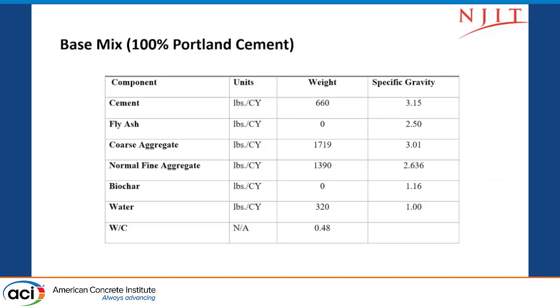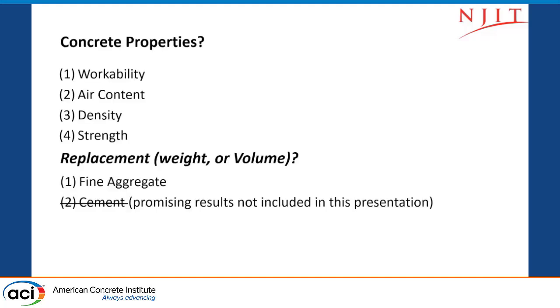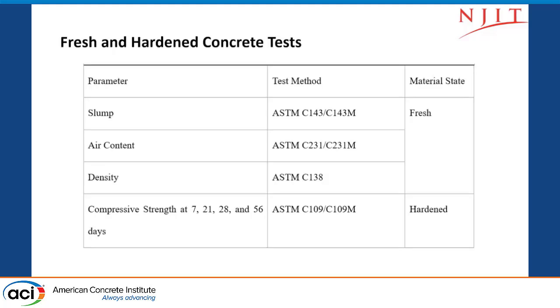So again, as we heard before, we did a 100% Portland cement specimen, and those are the characteristics of our specimen. We have fly ash, coarse aggregate, of course normal fine aggregate, and then the biochar and water, the water cement ratio, and those are the specific gravities on the side. We wanted to check the concrete properties: workability, air content, density, and strength. We said we are going to do replacement by weight of fine aggregate, and then replacement by weight of cement. We did the fine aggregate. We are working on the cement right now, but we didn't get the results yet. So it's promising results, but not included in this presentation.